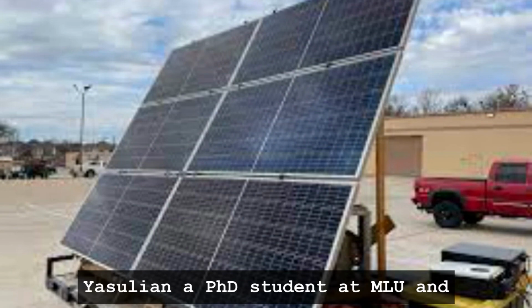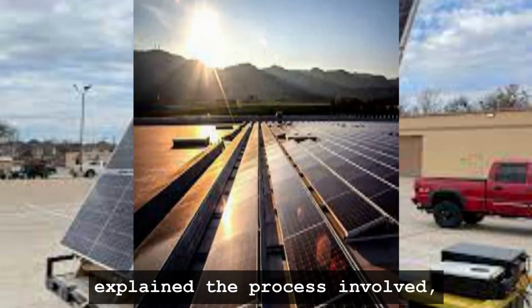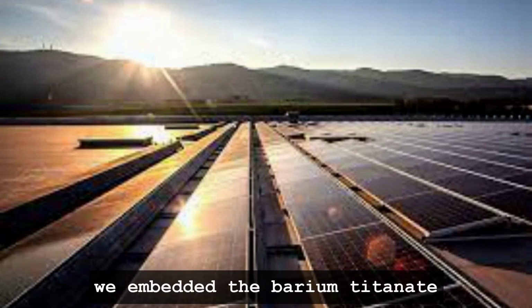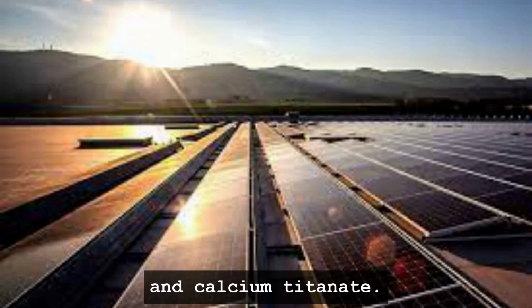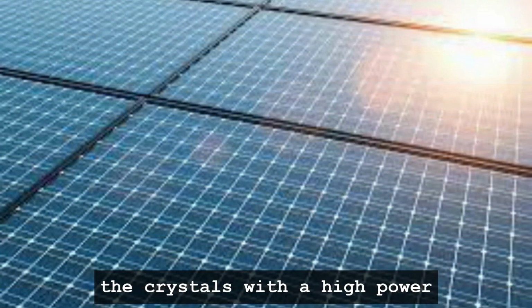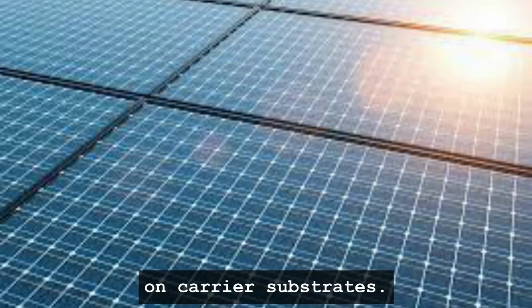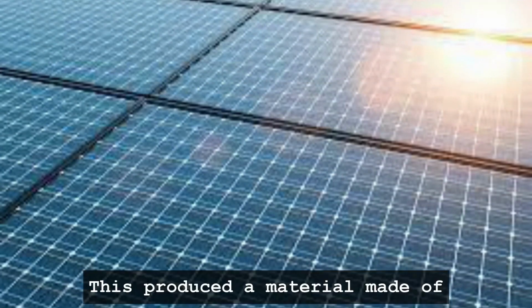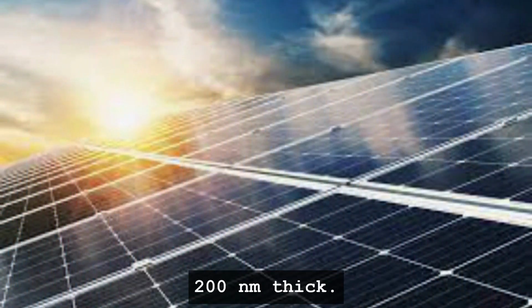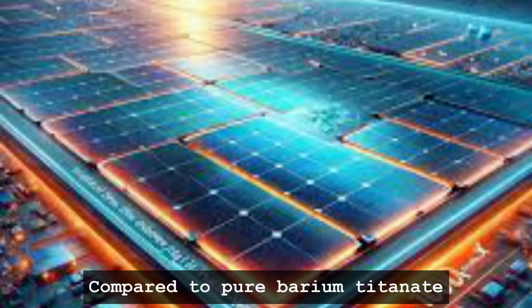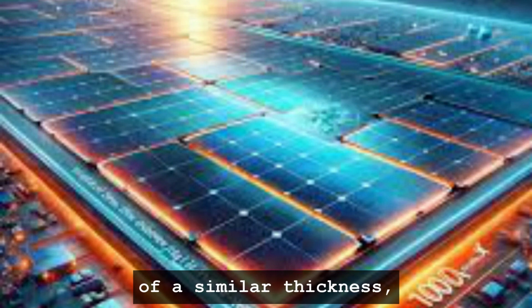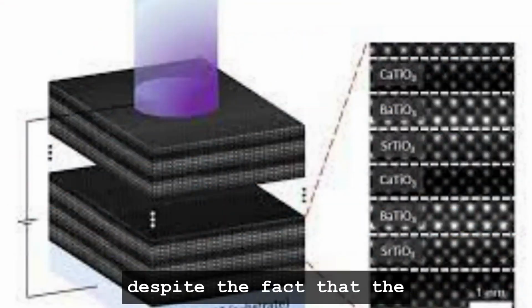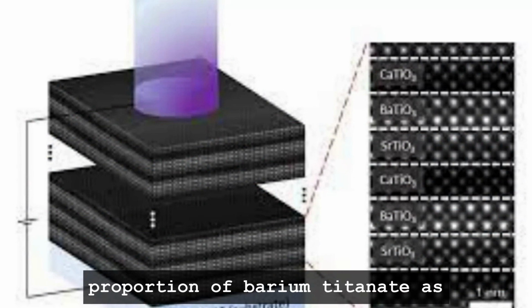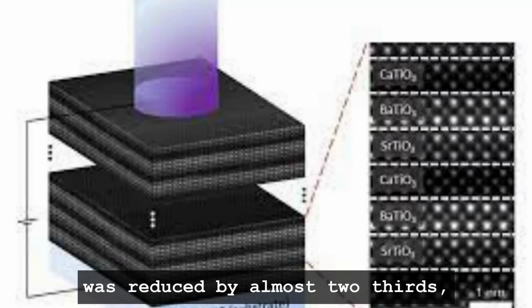Yeseul Yan, a PhD student at MLU and first author of the study, explained the process involved, stating, "We embedded the barium titanate between strontium titanate and calcium titanate. This was achieved by vaporizing the crystals with a high-power laser and redepositing them on carrier substrates. This produced a material made of 500 layers that is about 200 nanometers thick. When conducting the photoelectric measurements, the new material was irradiated with laser light. The results surprised even the research group. Compared to pure barium titanate of a similar thickness, the current flow was up to 1,000 times stronger, despite the fact that the proportion of barium titanate as the main photoelectric component was reduced by almost two-thirds."